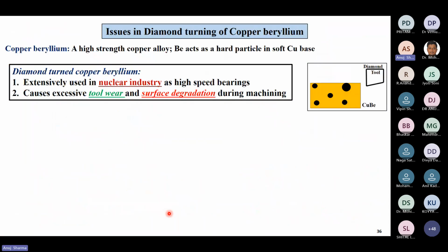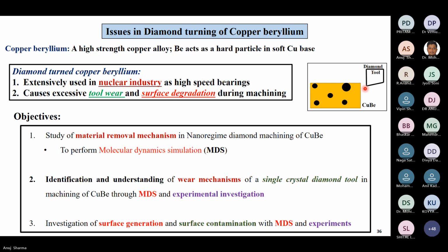Similarly, I studied copper beryllium. Copper beryllium acts as very hard particles inside the copper matrix. This material is extensively used in nuclear industries as high-speed bearings, but it has the limitation that it can cause excessive tool wear and surface degradation, because during machining these hard particles encountered with the workpiece cause tool wear.